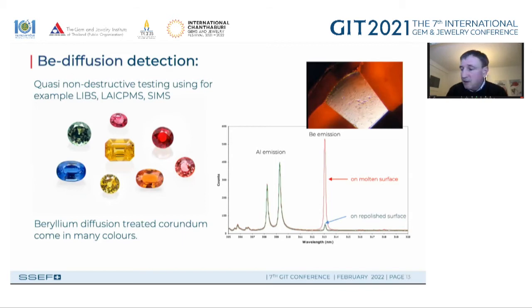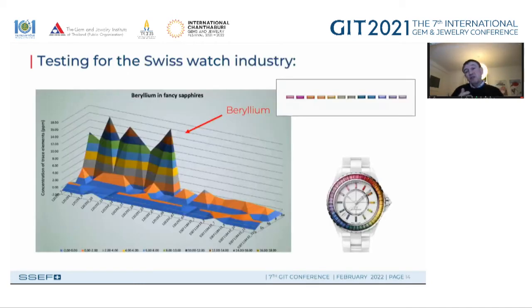If we look at treatments, a classic example would be beryllium diffusion treatment. To detect this treatment, normally we need a tiny amount ablated from the stone, so as to be able to analyze it chemically. And you can use, for example, LIBS, as you see in this spectrum with a beryllium emission line, or laser ablation ICP mass spectrometry.